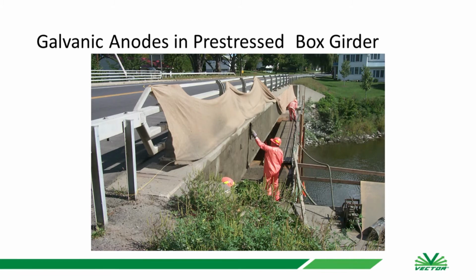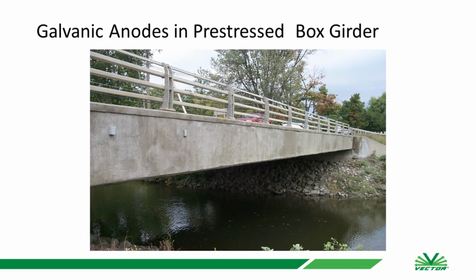So you do need a steel-to-steel attachment for these to work, but you can attach them at one end of the series and another at the other end for redundancy, because if we lose one connection, then we have a whole string of anodes not doing anything. All they do then is they'll grout everything over, and that's what it looked like when it was completed. Real nice that for these galvanic solutions, you do not have to monitor them. There's no maintenance that's required. You can kind of put them in there, set them, and forget about them.